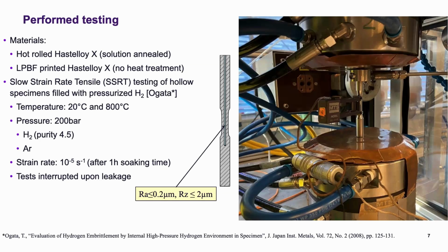But that being said, I was talking previously about the component loading and how to predict the cyclic life is really our challenge. And what does a slow strain rate test really tell us about the fatigue life? It's a quite bold assumption that we can have a correlation between the ductility in the slow strain rate tensile test and the fatigue resistance. So that's why we need to be able to do fatigue testing.